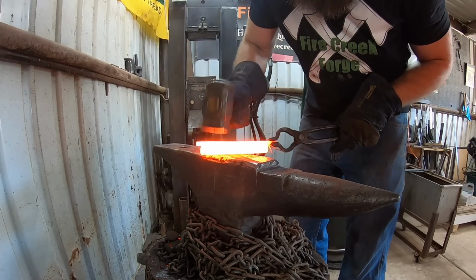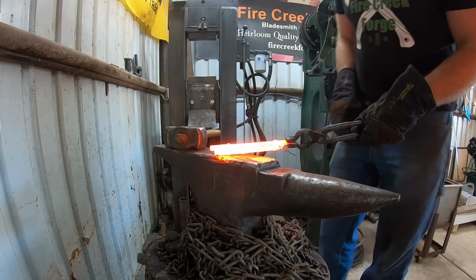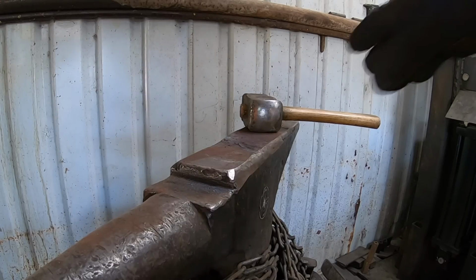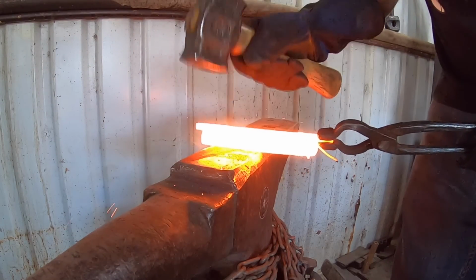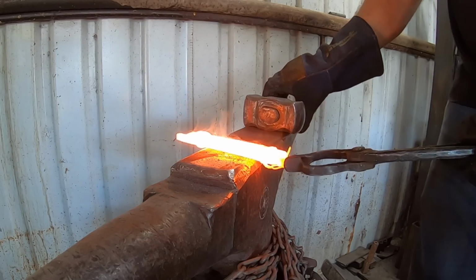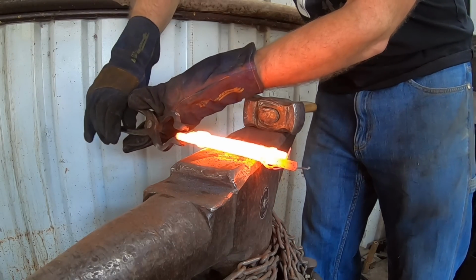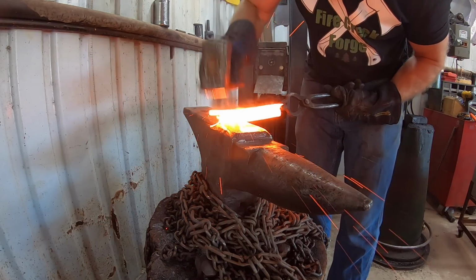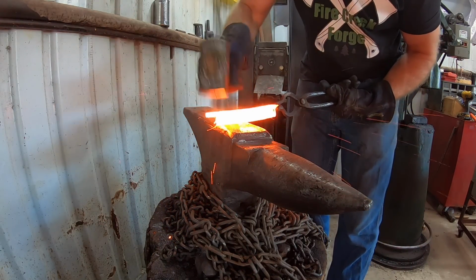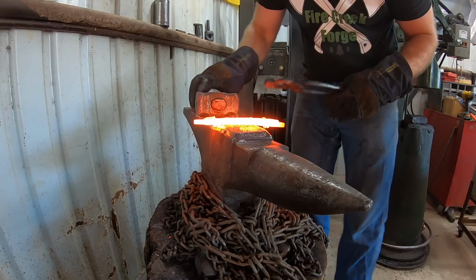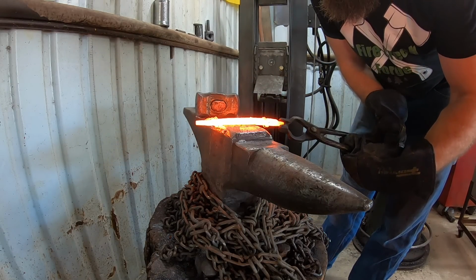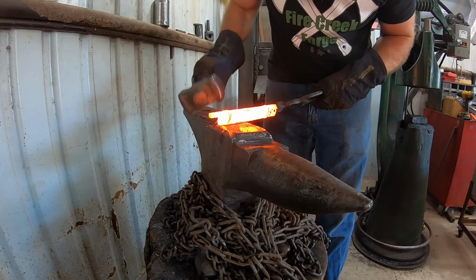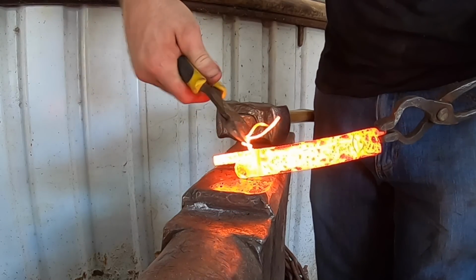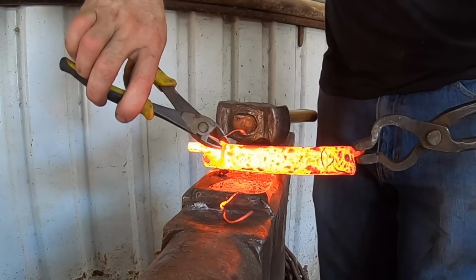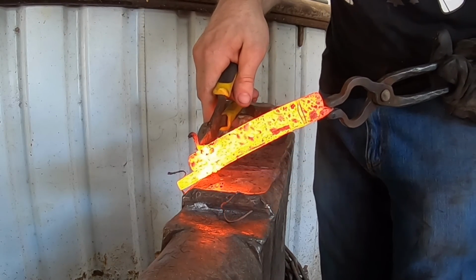You'll notice that I started in the middle and worked out towards the end, and then came back and worked towards the other end. That was on purpose so that we can force out any flux and any other impurities out the ends, instead of potentially trapping them. I could have also worked from one end to the other and achieved the same thing. So I need to swap ends a couple times and get this welded, because the end that I address immediately upon removing from the forge has the heat, and once you move to the other end, it's lost a little bit of heat. So you want to make sure that you have everything welded up properly.